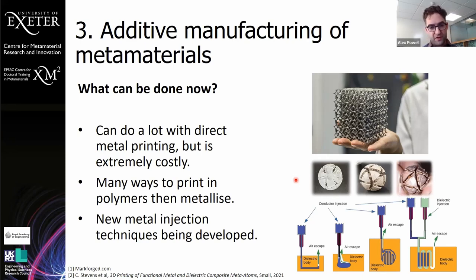And then a group at Oxford who we've done some work with have also come up with a different way of doing metal injection, where instead of injecting inks where you have to worry about the solvent escaping, they've used metals, or one called Field's metal, with a melting temperature around 60 degrees. And so they 3D print their mold and then inject the metallic inclusion into the mold at around 70 degrees, which is way above the melting temperature of this metal, but way below the glass transition temperature of the polymers where they start to deform. And so they're able to make fairly complex metallic inclusions that way. So that's another route that maybe has some potential. But for now, it's very difficult.